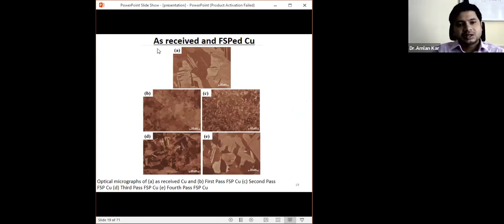So this is the as-received copper and processed copper without the polymer particle or the ceramic particle. You can see that this is the base metal microstructure, where the grain size was approximately 20 microns. After the first pass, second pass, third pass, and fourth pass, you can see that after the second pass you get a very good refinement of the grain structure. But if you go for further processing, because of the higher heat input,